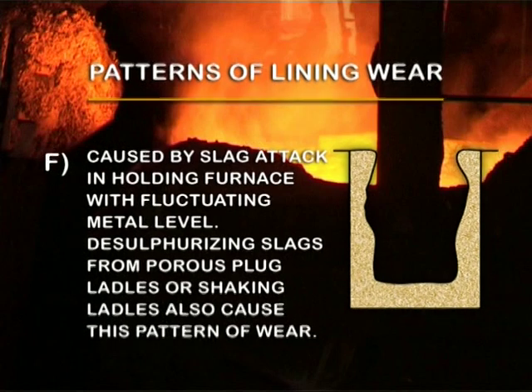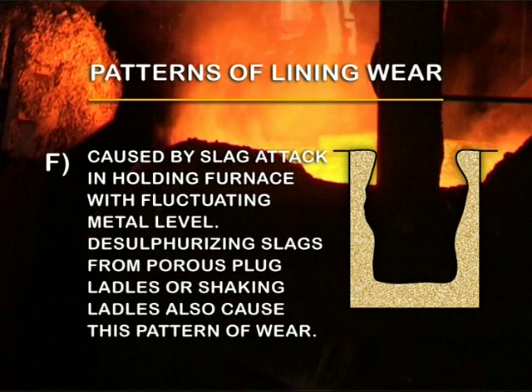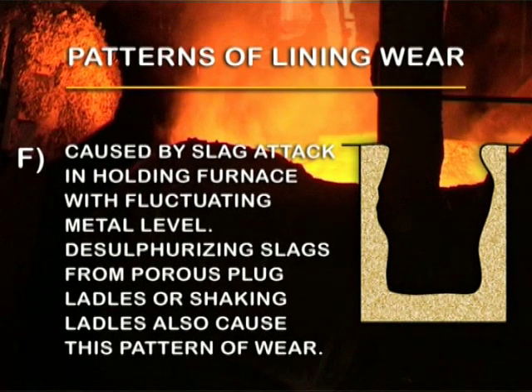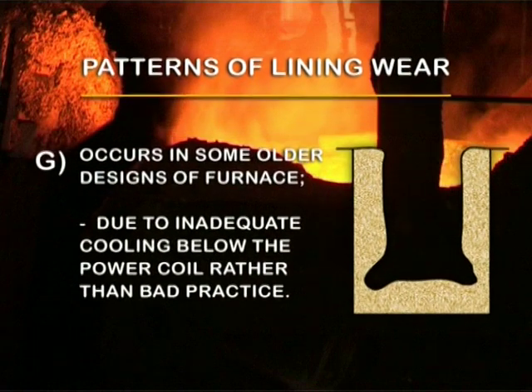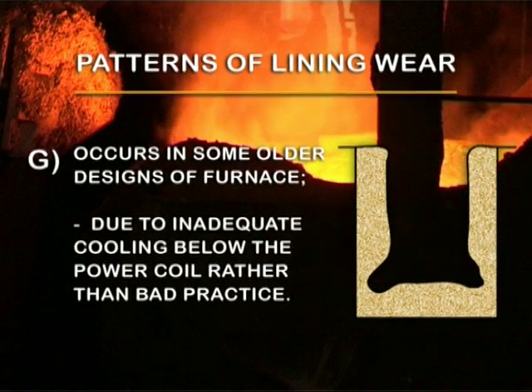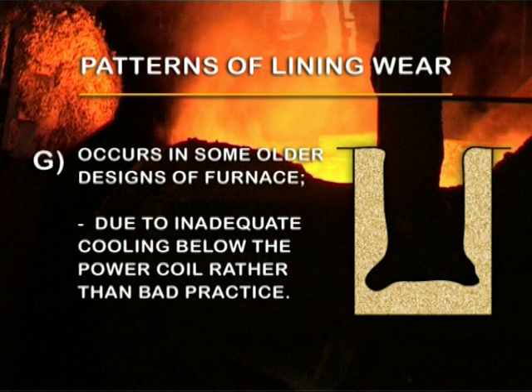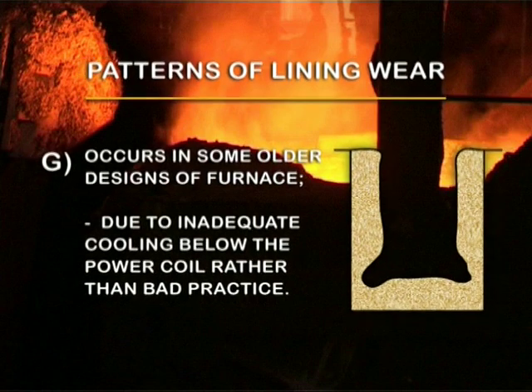Caused by slag attack in holding furnace with fluctuating metal level. Desulfurizing slags from porous plugged ladles or shaking ladles also cause this pattern of wear. Occurs in some older designs of furnace due to inadequate cooling below the power coil rather than bad practice.